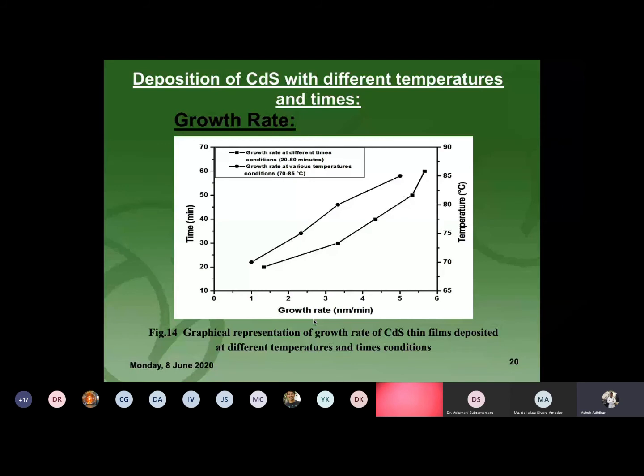growth of the film. It is seen from graph 14 that the growth rate of the film is increasing with the increase in temperature and time, which is due to the kinetic enhancement of the reactions through increasing ion mobility.